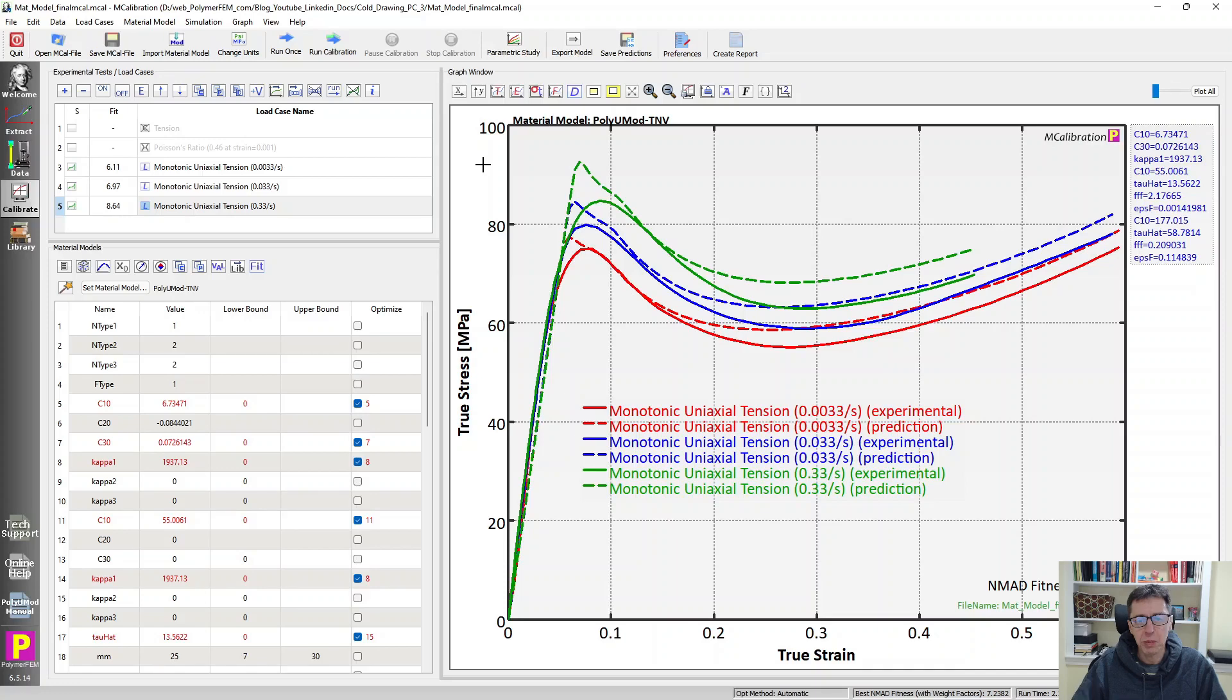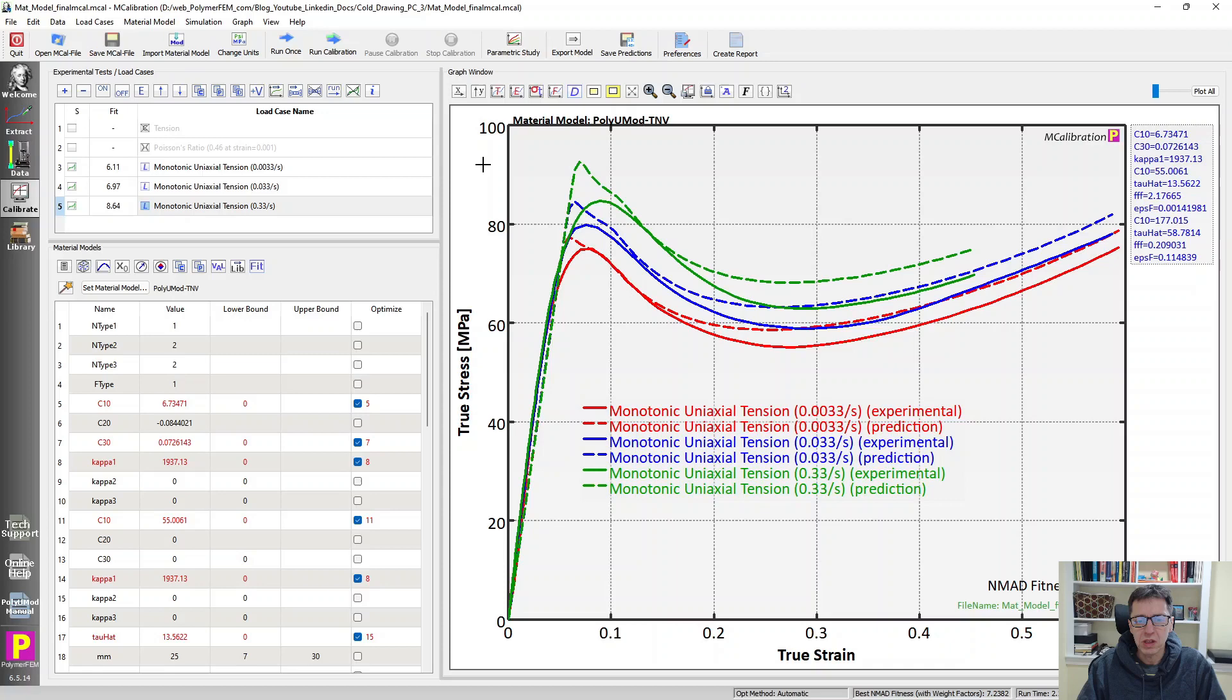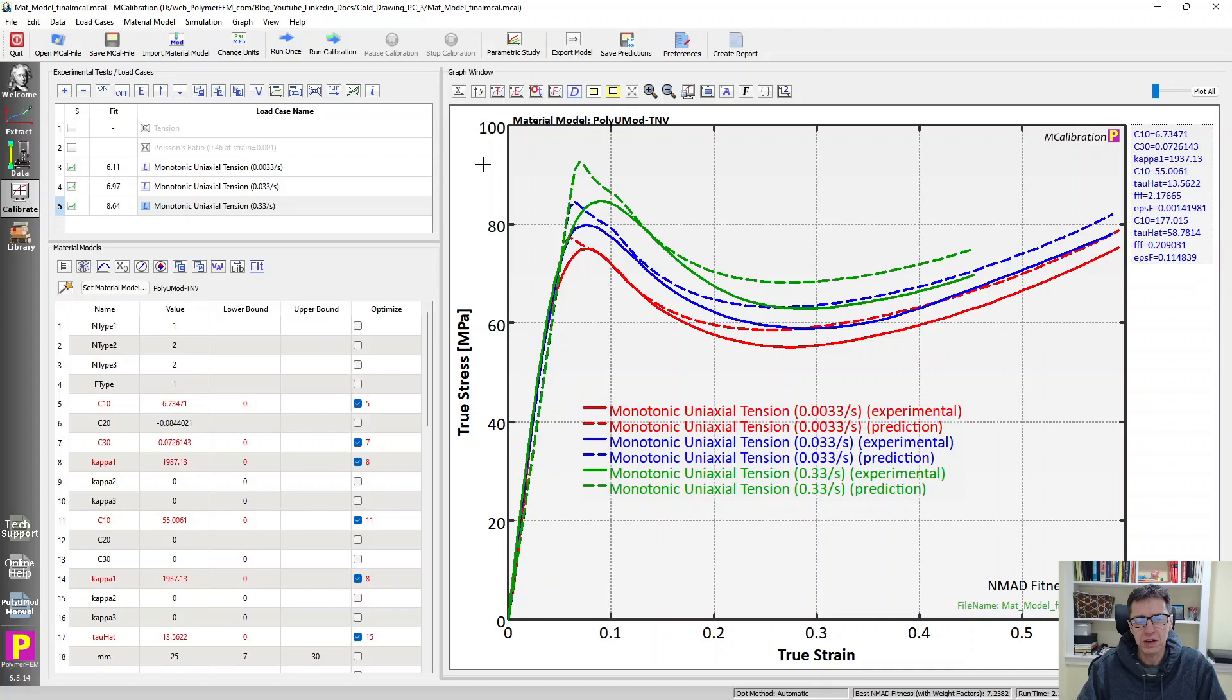It's a little time consuming, and you don't need to do this if the material does not neck. If it doesn't neck, it is much quicker to simply extract the force displacement or stress strain from that using DIC in your real experiments. But if you do have necking, it's really hard to analyze that data, as I showed. In that case, using the approach that I showed here would be a preferred method in order to get an accurate material model.